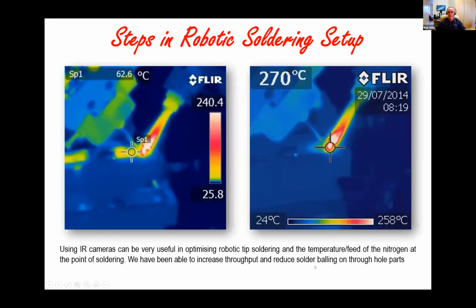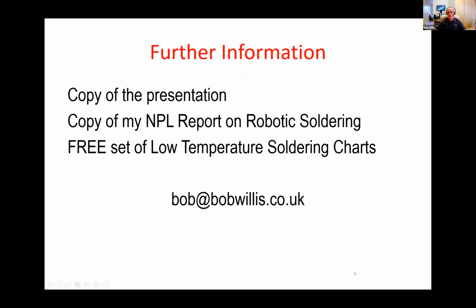A couple of other things that can be beneficial using IR technology. And using IR measurement technology, simple systems that you can see here, it's good to see what temperatures are actually being achieved on a printed circuit board with non-contact during a robotic soldering operation. But also looking at the feed rate of nitrogen, the temperature of nitrogen coming into the process, and how that can improve and speed up the process is quite a good quality control tool to look at if you're looking at the use of robotic soldering in your process.